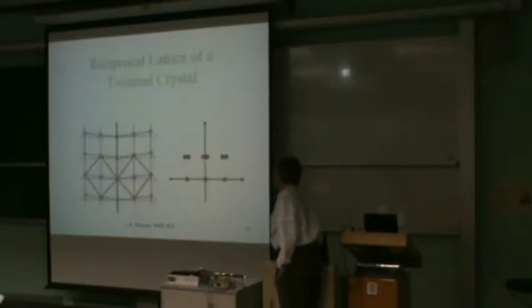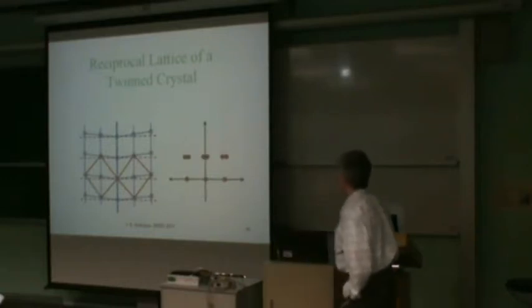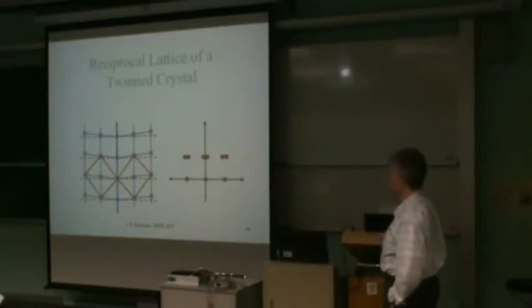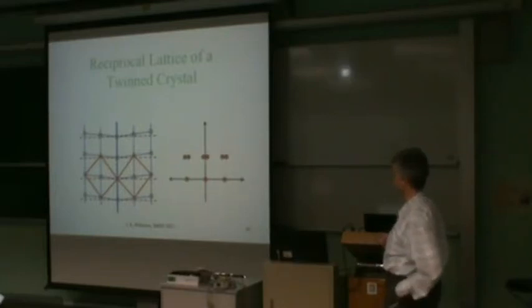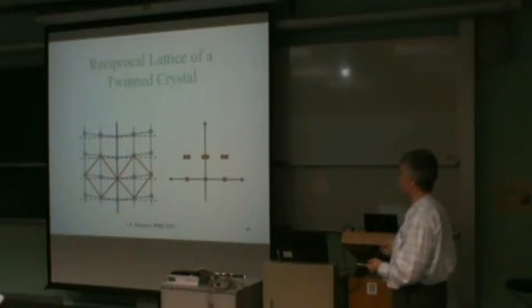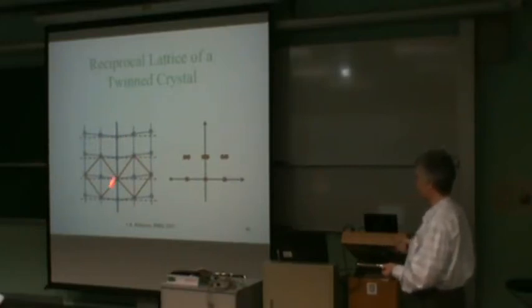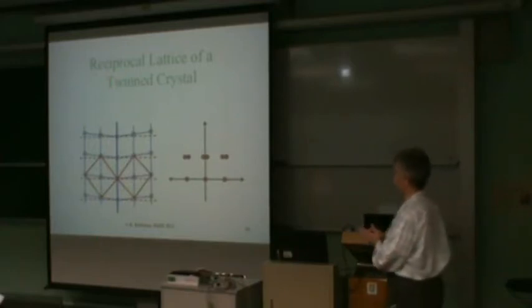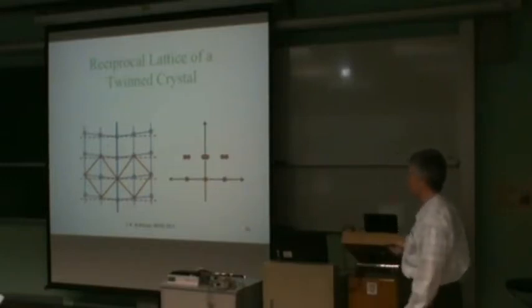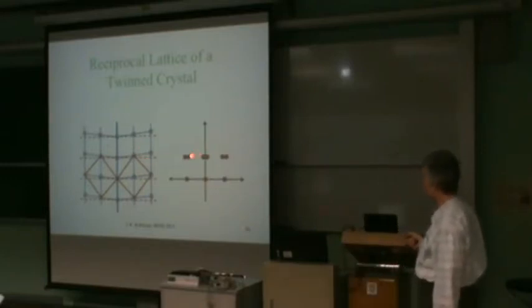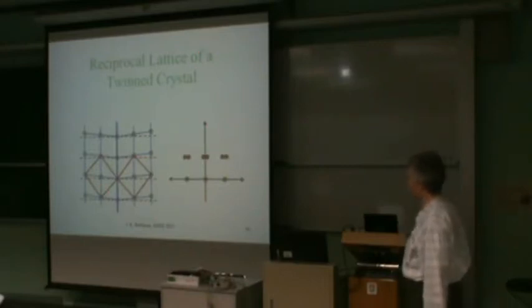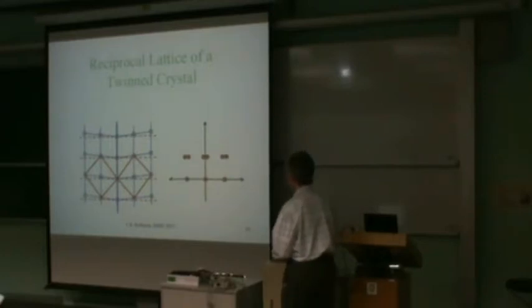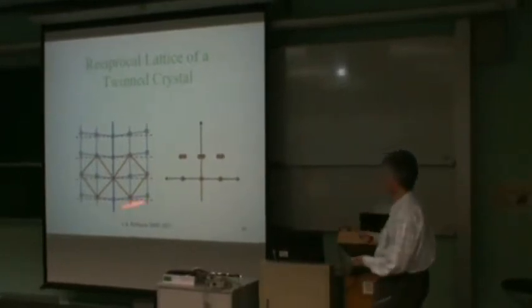as you'll see. Okay, so one example would be what you get with twinning. So if you have a tetragonal crystal structure, then you can have two directions of the tetragonal distortion. And if you look at a fault that would occur where the two domains meet, you would have a twinning phenomenon taking place. And the way you would see it would be, in traditional diffraction, you would see splitting of the Bragg peaks in the direction along which the twinning axis is occurring. And if you do this coherently, you get an image of the whole thing.